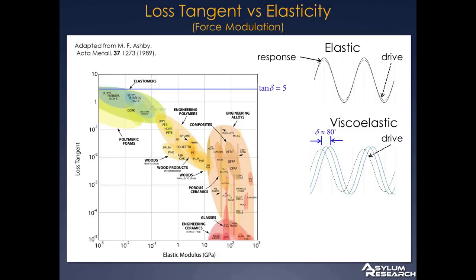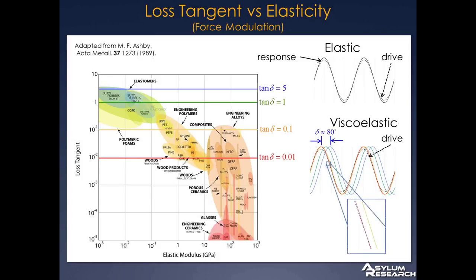If we reduce that phase angle a little bit, this green curve here gives us a loss tangent of 1, so it's still in the elastomers. We can further reduce it. There's 0.1, so that's maybe more typical for polymers. We start to see that the phase angle is getting a little more difficult to measure. We'll reduce it even further down to 0.01, and you see that it gets quite hard to separate from the in-phase component. Again, since it's a logarithmic scale, that phase angle becomes very, very tiny. And I zoomed in there just so you can see that.